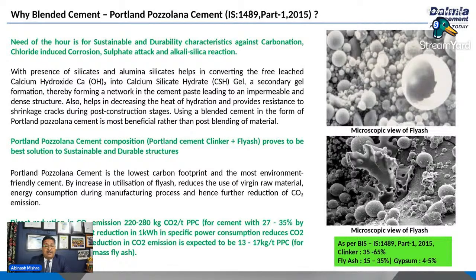So the question is whether we are going to continue with OPC cement and fly ash, which doesn't have a method of control of total sulfur content, total trace mineral content, total metal content. We do not have anything. We just add and make the concrete and say, make it set so that it produces a structure as governed by codes. But what about durability, concrete cover life, and others? Here, if you use PPC cement in your site, made with graded fly ash, tested and prepared to survive weathering conditions, it will definitely add value to you. Yes, there are questions: OPC plus fly ash gives good cost benefit. It doesn't give good cost benefit.